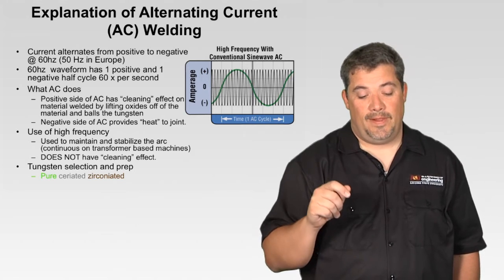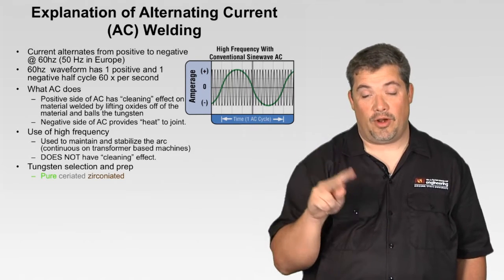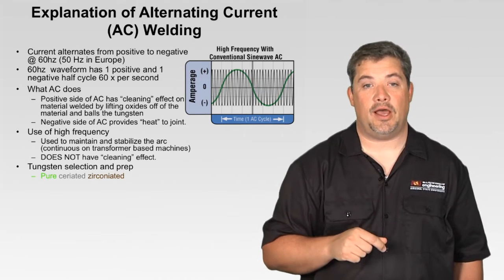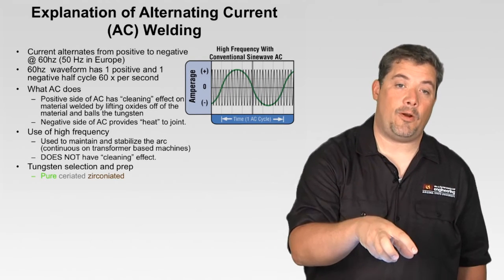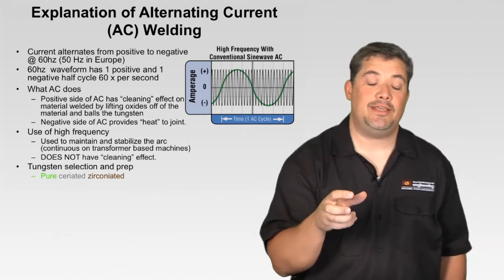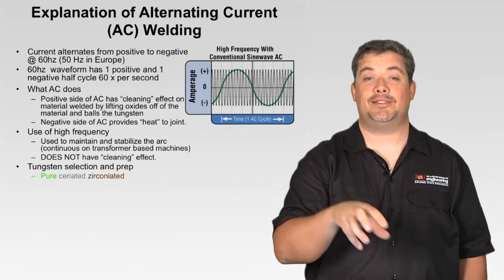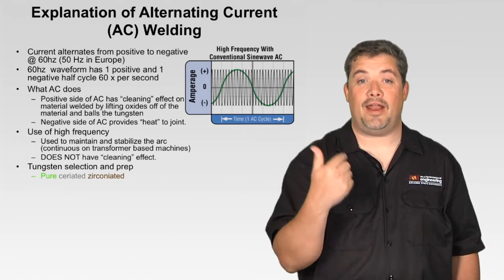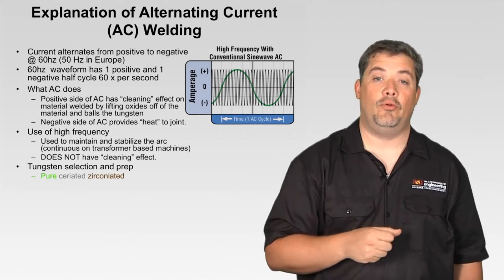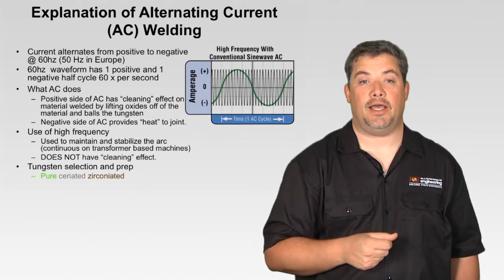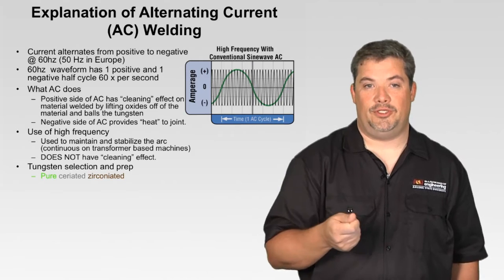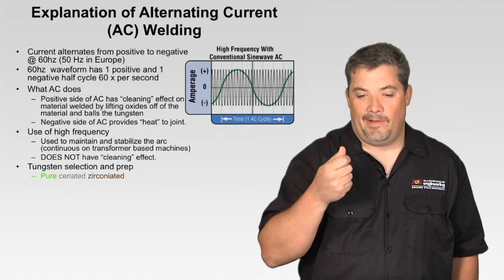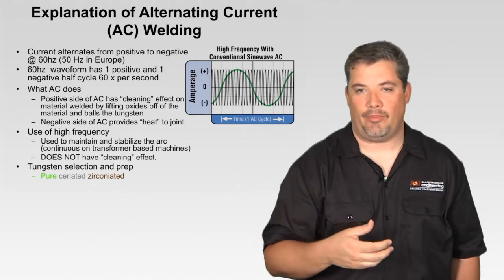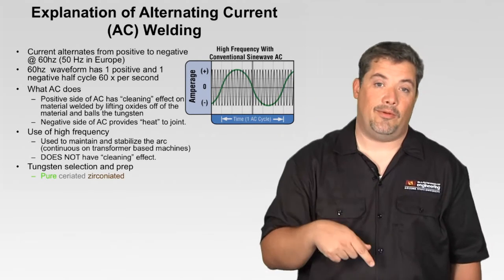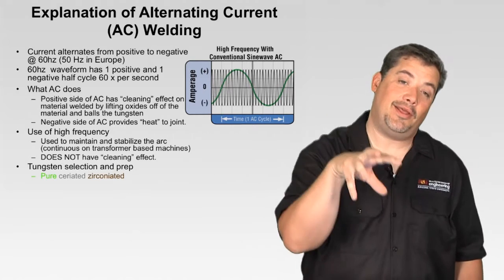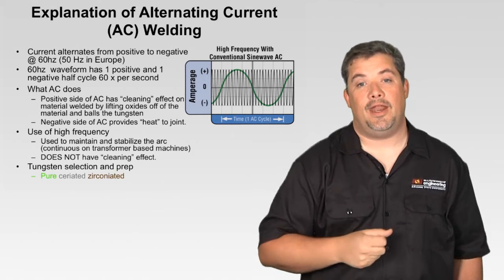So what does AC do? The positive side of the AC has that cleaning or etching effect on the oxides that we just talked about, and the negative provides the heat to the part. So that's why we use AC for aluminum, because that heavy oxide layer exists, and that electrode positive gets rid of that oxide layer for me, so I have a good, clean, beautiful weld that's minimized how much oxide is there. But if I do it with just DC electrode positive, I'm using giant tungstens. It's taking forever to heat the part. I'm getting oxide out, but I'm not putting a puddle down. So I need to throw some negative in there to put some heat on to get the puddle there, but I need that positive to clean and etch it.